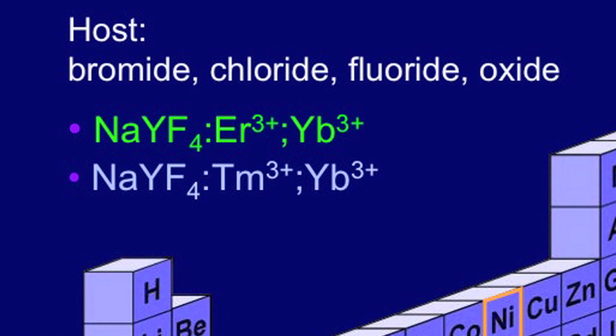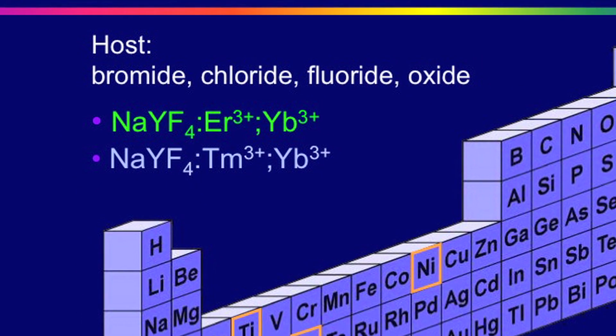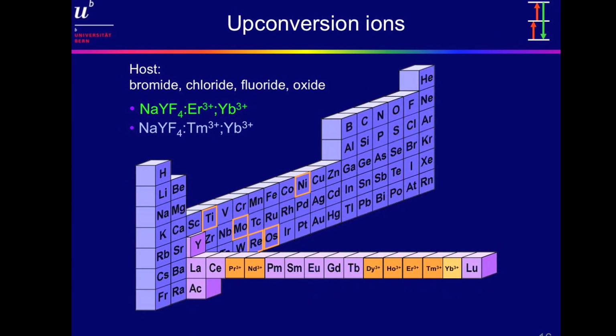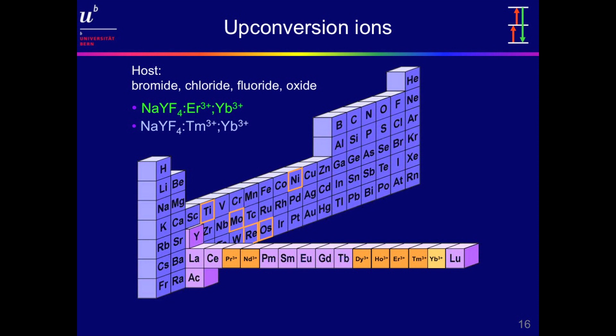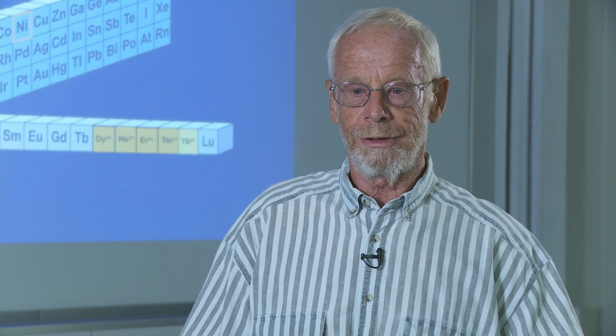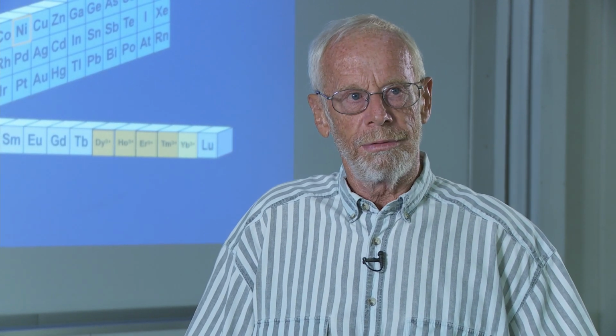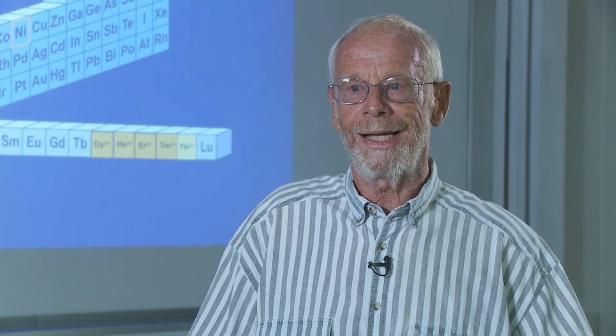We played around with sodium yttrium fluoride, sodium gadolinium fluoride, sodium lanthanum fluoride, doped with all kinds of lanthanides, combinations of lanthanides, lanthanide transition metals. We did a lot of rather sophisticated spectroscopy, time-resolved, 1-color, 2-color excitation as a function of temperature. And we did learn a few things about mechanisms. We also came up with a tentative explanation why these lattices are particularly suited for upconversion. I'm going to skip all this and jump directly to my last scientific slide.